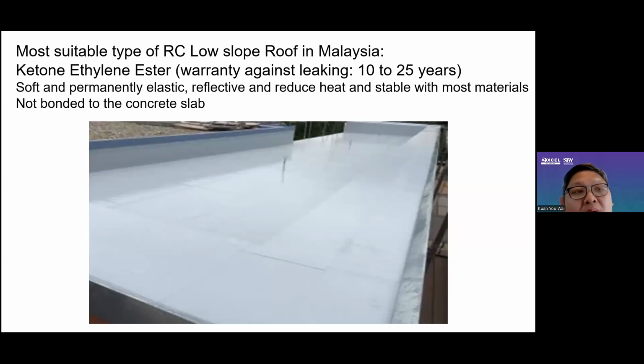So far, I discovered Ketone Ethylene Ester is still the best waterproofing membrane for Malaysia, which can carry up to 10 years to 25 years warranty. It is soft in nature, permanently elastic, and due to the white color, it actually reduces the heat, and as a result, it also reduces the impact of expansion and contraction as a result of heat. Furthermore, it is not bonded to the concrete surface, so any cracking or any movement to the concrete doesn't affect the waterproofing. So this is how good it is, and in fact, it is the result of the previous failure of, let's say, polymer coating, torch membrane, and even built-up roof. So this is the best so far that I can notice for the Malaysian environment due to the ability to cool down the roof.